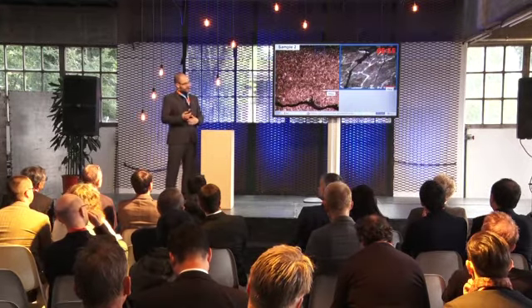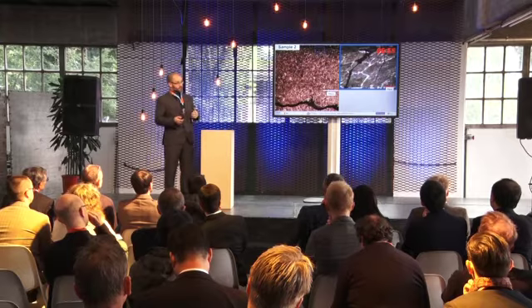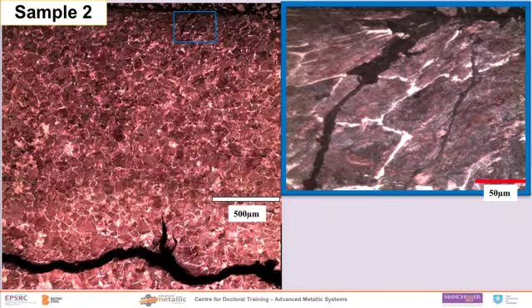Here we're taking another look at vertical cracks within a different sample, and here you can see the vertical crack starting at the top, but it's also growing up towards it from the bottom as well. And zooming in on the crack, that crack's actually cutting across grains. Now with a typical squat, you'd expect it to follow the ferrite around the grains because it's easier, but because of the thermal damage, it's cutting across the grain instead.